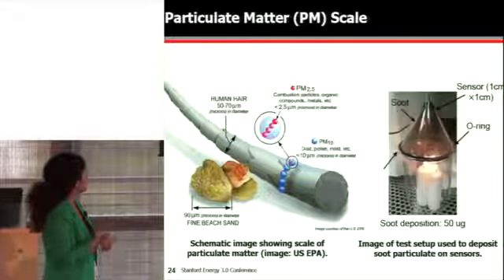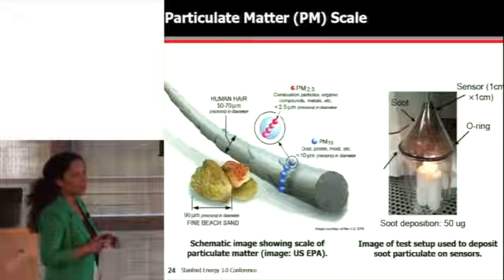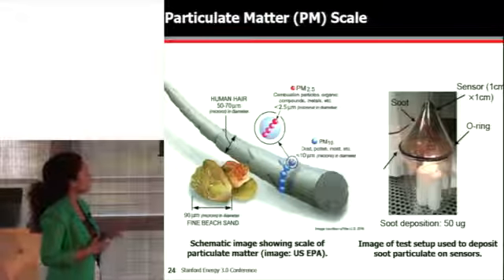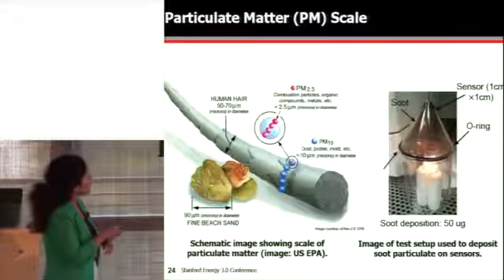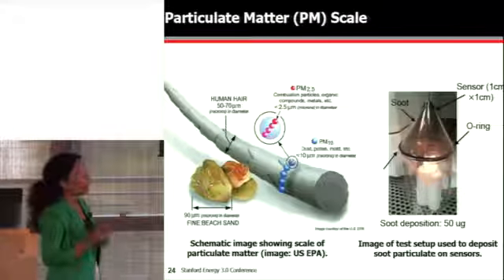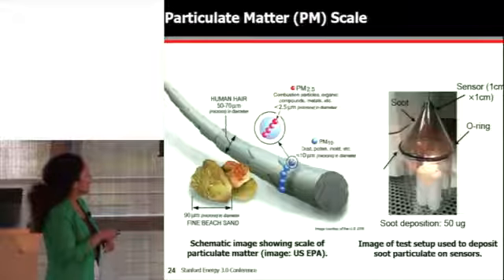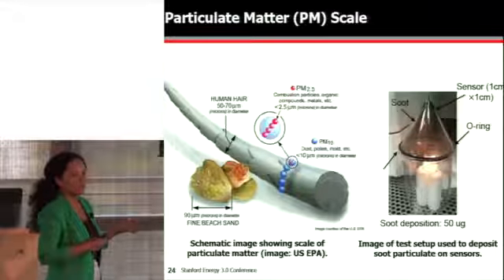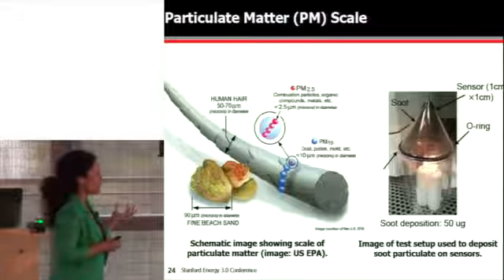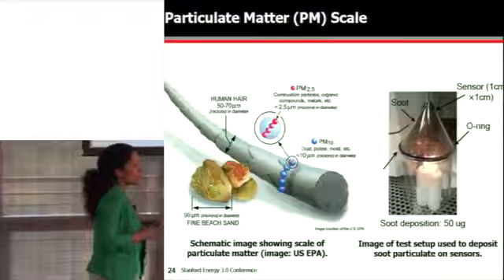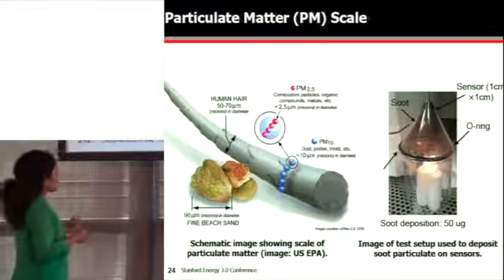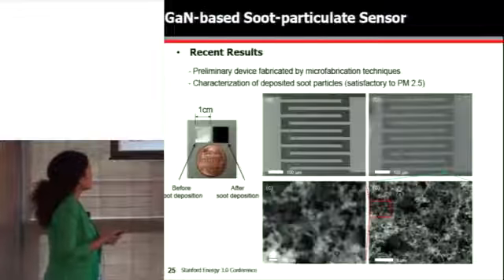Just to give you a feeling for the length scale, this is just an image of a human hair. Again, the diameter is between 50 and 70 micron. The harmful soot particulates that we're concerned about are usually in the 2.5 micron scale. So that lends itself well to micro and nanoscale sensing technology. So in my laboratory, we've made a very crude soot particulate generator. We use candles, actually. What's interesting is that paraffin candles actually deposit positive charge, and candles made from beeswax deposit negative charge. And so we're using this to create soot in a controlled environment.